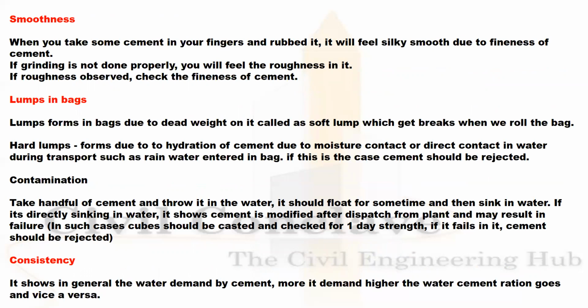It should not have any roughness. If roughness has been observed, check the fineness of the cement. Lumps. Lumps form in bags due to dead weight, or what is called a soft lump, which we break in the bag. Hard lumps form due to the hydration of the cement, due to moisture contact or direct contact with water during transportation or rainwater. Okay. In that case, the cement should be rejected.